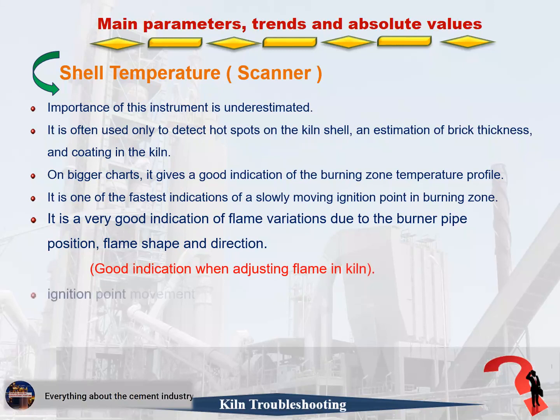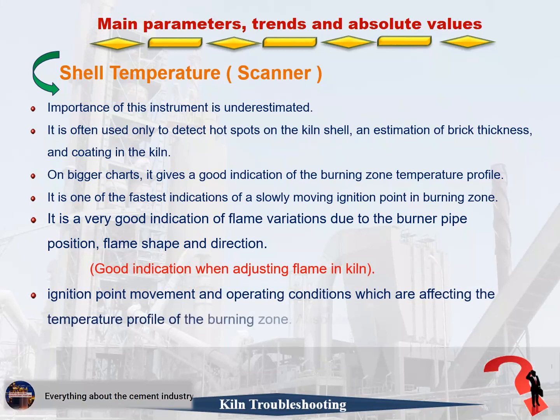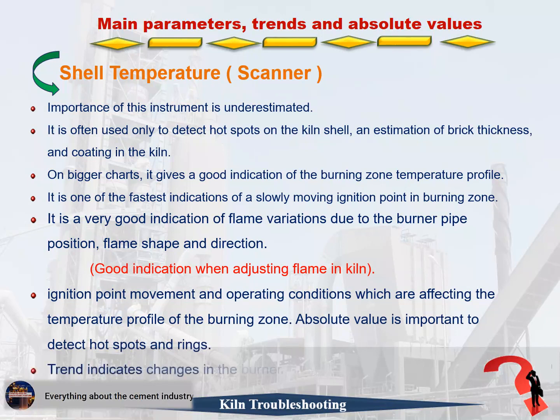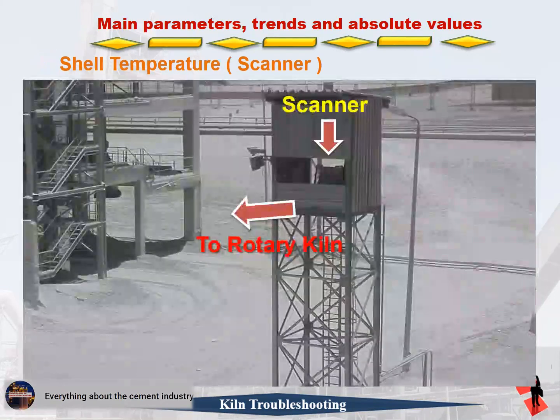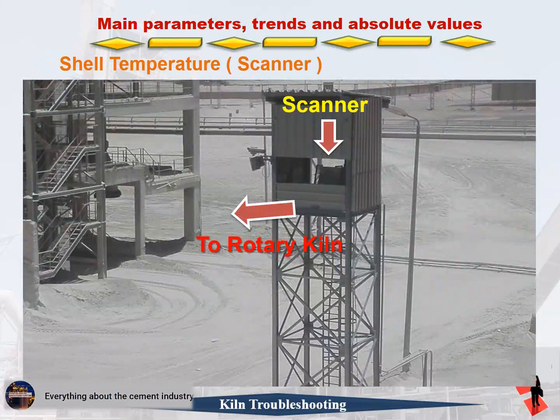6. Ignition point movement and operating conditions which are affecting the temperature profile of the burning zone. Absolute value is important to detect hot spots and rings. Trend indicates changes in the burner system, kiln speed. This picture shows shell temperature scanner.